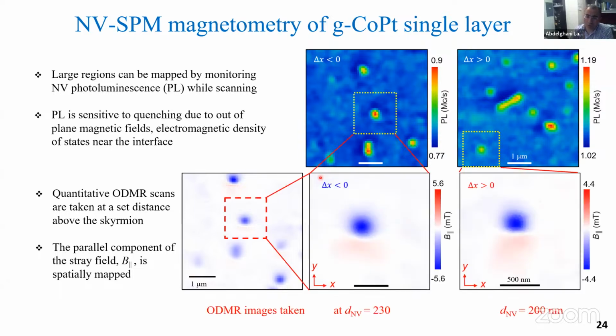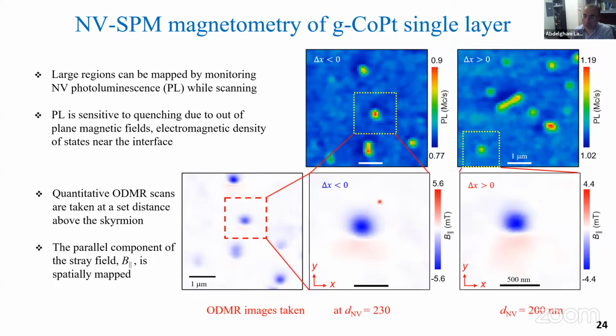So now one can zoom. If you look here, this is PL, and this is ODMR. These two skyrmions correspond very well. But if you want to zoom in exactly on a given spin texture, you work at a certain standoff, in this case 200 or 230 nanometers. You can map nicely. You see these isolated spin textures or skyrmions, with blue usually negative and red positive. The stray field is significant. We're talking 5.6 millitesla, even at 230 nanometers. If you get lower, you can get even to 100 millitesla. So this works very well.